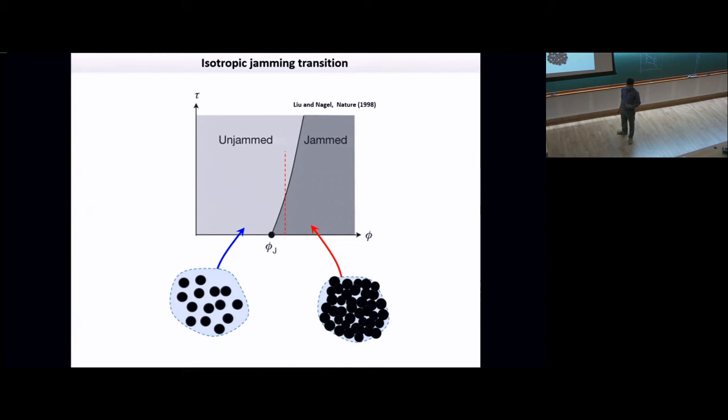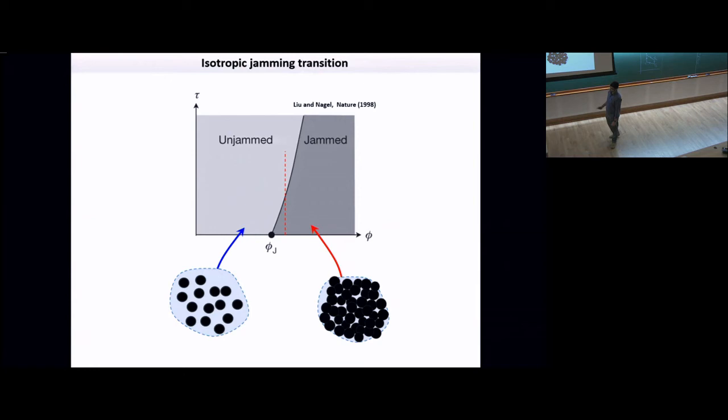But the problem was, in our case, we are not adding extra particles, right? Everything is happening under force. Also, our pulling speeds or deformation speeds are well below the sound propagation speed in this material, so we are not compressing the system locally also. Although this is a very well-established theory of how a material can go from a liquid-like to solid-like state, this is not likely the mechanism in our case.